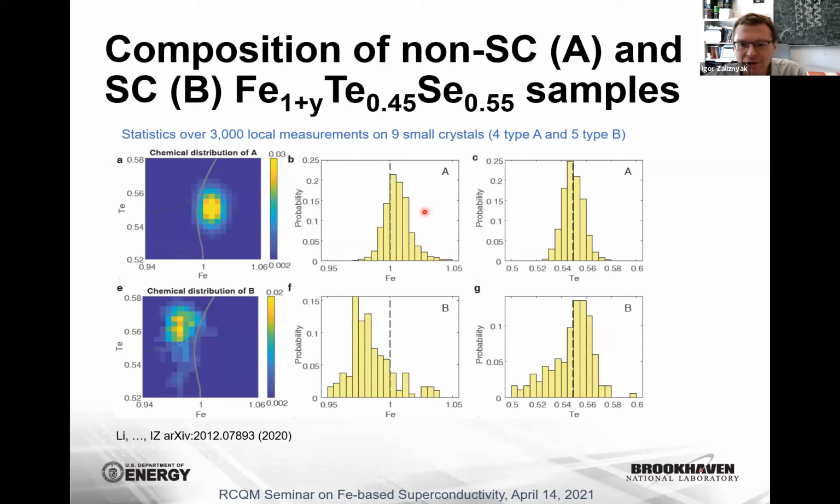little. So this is a histogram of iron distribution. The superconducting sample is slightly less homogeneous, as you can see, but the average iron composition is probably 0.98. So first of all, it's iron deficient. Of course, we are not 100% sure that it's 0.98. It might be 1.01, or maybe 1. The absolute accuracy of our measurement, which is EDS, is not so great.